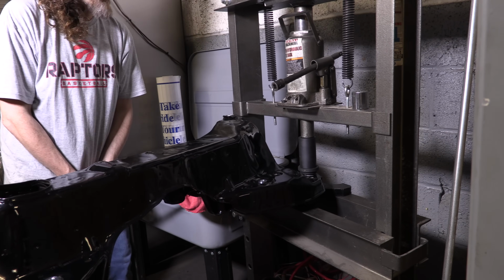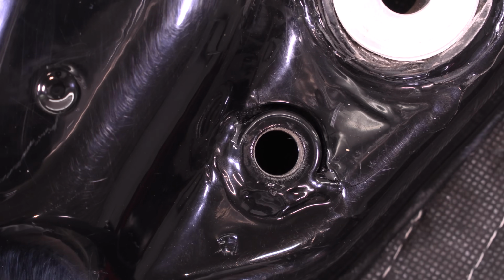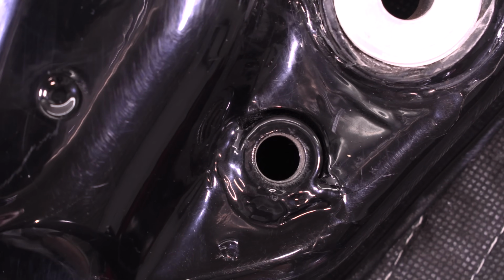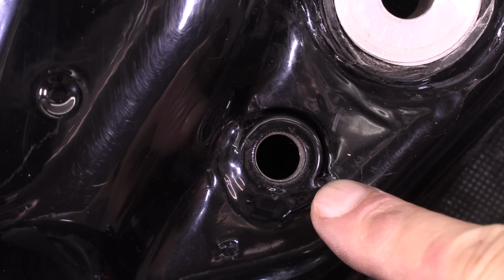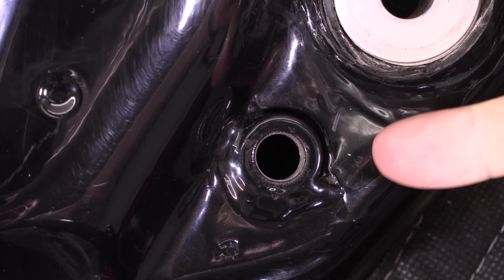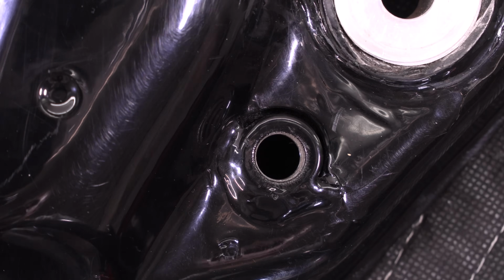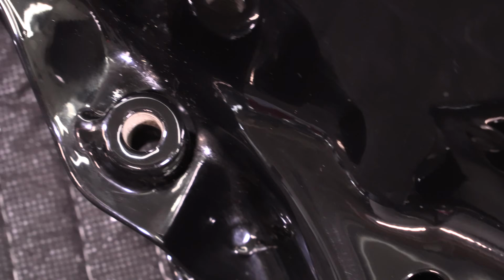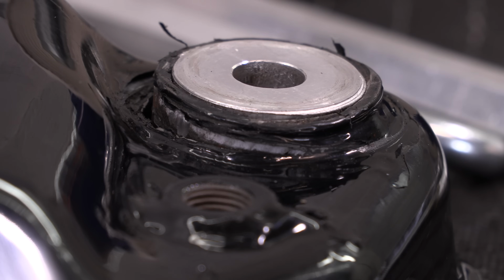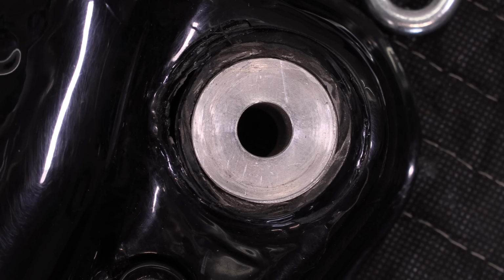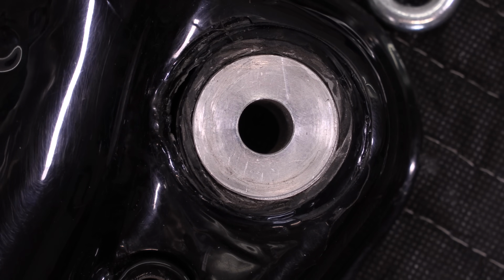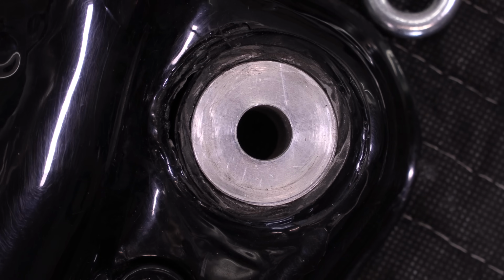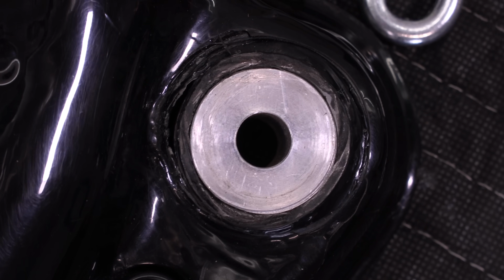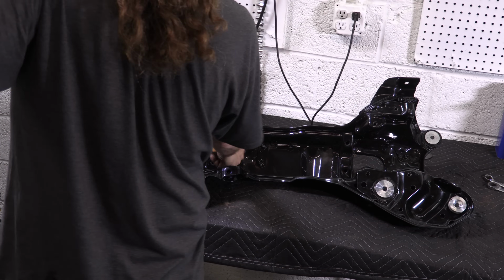There's a logical explanation for this regarding where the robot can reach and even weld. If you look closely at the subframe holes where the bolt bosses or the bushing bosses are all welded in, the robot only welded halfway around it because it couldn't reach the back side of the thing to weld it. One side of this bushing was welded poorly, and it's because it was nestled into a corner. Since it wasn't fully supported all the way around, it ripped out and went the direction it most easily could under all that load. And it didn't just tweak the boss, it actually bent my subframe too.